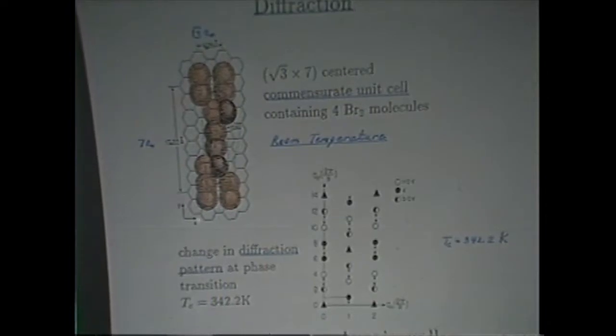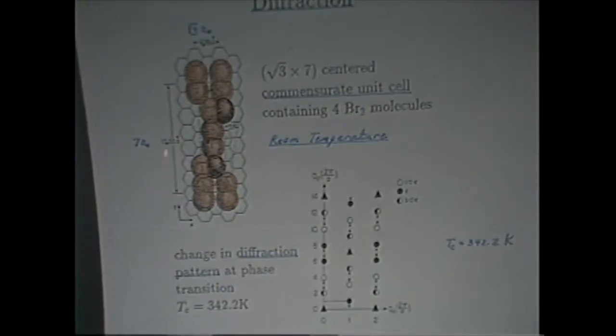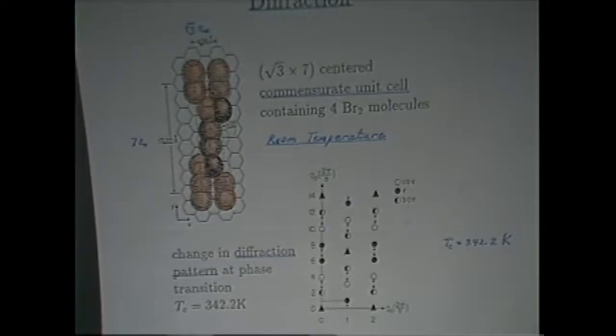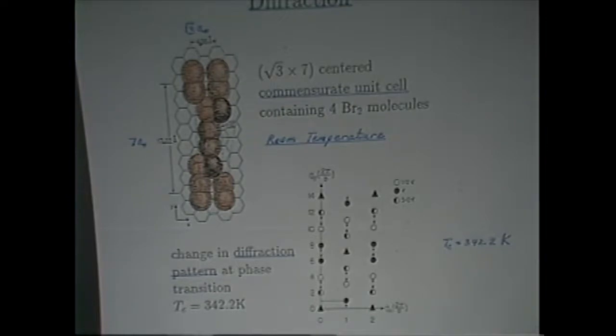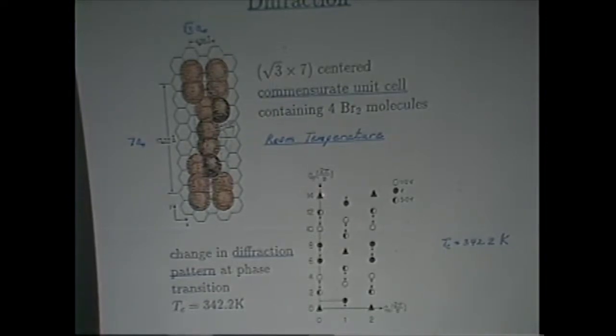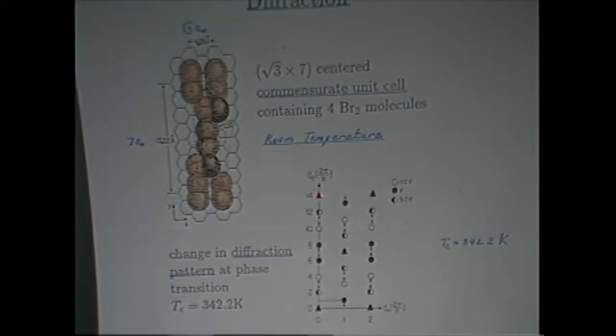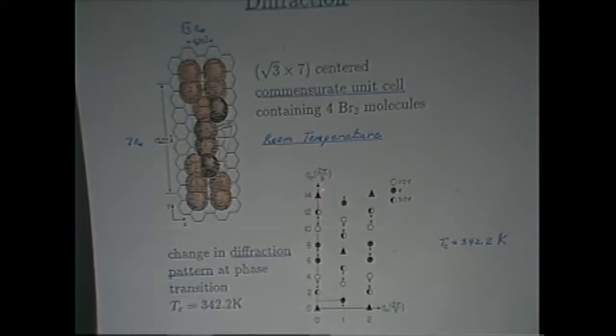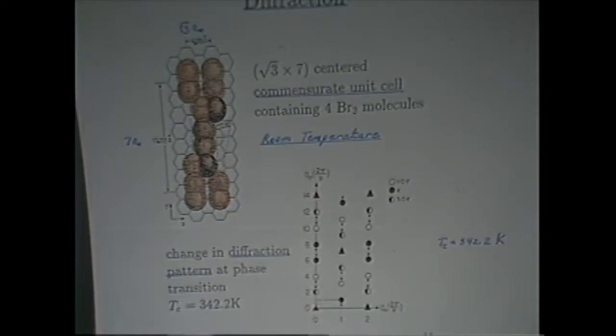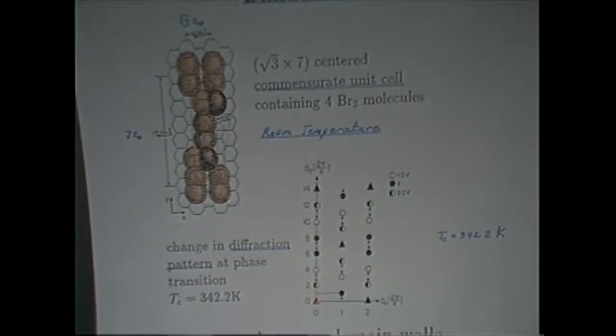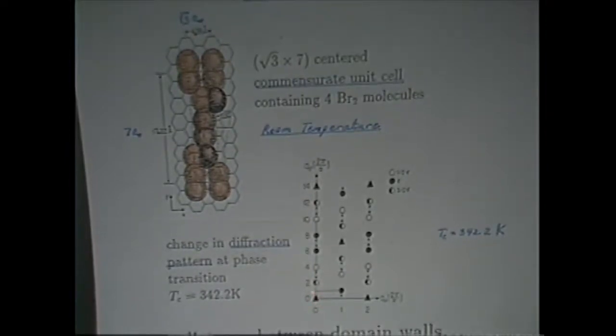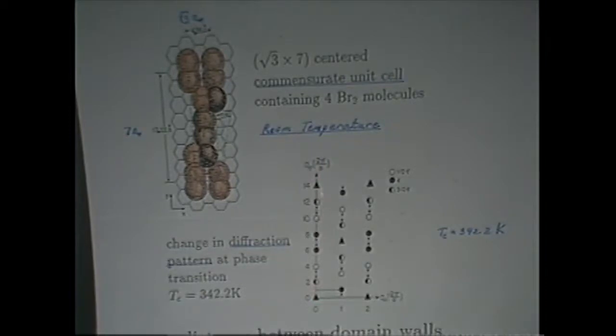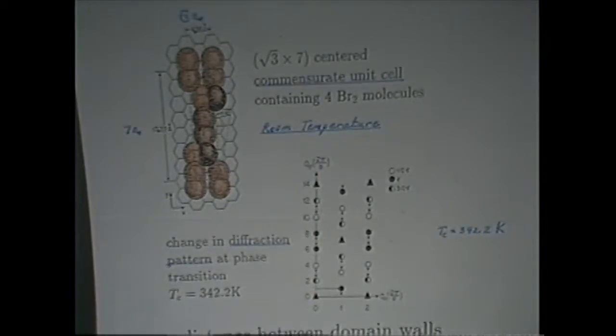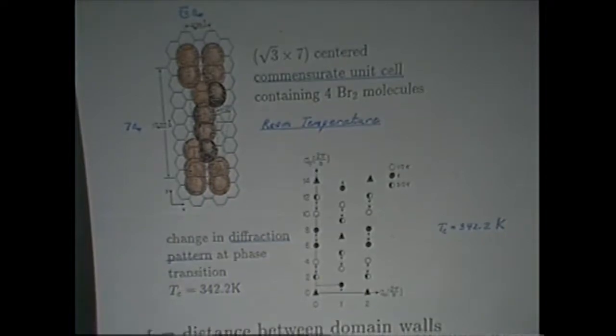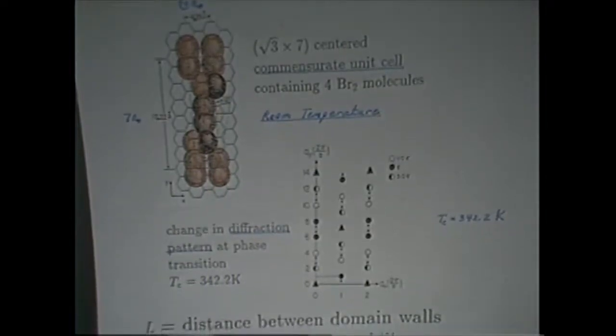In the direction of this large part of the unit cell, 7 times the graphite lattice constant, that's the direction in which the stripe domain phase gets established. Here are the diffraction spots shown schematically. The triangles correspond to the graphite spots. So between these two graphite spots, we divide the unit into 7 equal parts, and we put spots. These spots here are the spots of the superlattice. And they're equally spaced for the case of the commensurate unit cell.